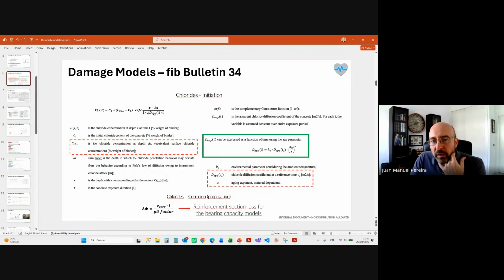And this correlates to this thing. This thing is the apparent chloride diffusion coefficient. And this is something that depends on the weather with this K, and changes with time with this alpha, which is the aging exponent, that thing we calculated before. Most people use this model as a deterministic model, which is not what the FIB intended. Each of these parameters has a distribution of probabilities with a standard deviation, et cetera. So you should do probabilistic modeling on this.